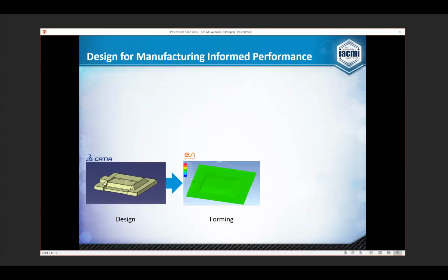So one thing we want to do is model the forming process. Orientation state, as we've talked about before, is really critical in these parts, but also the shearing behavior, how it introduces wrinkling, how it shows those different effects, and how that's going to be different for the RFF fabric, since we don't have the interweaving of the tows as you would have in a twill fabric. It's going to have a different shearing behavior that we want to understand.